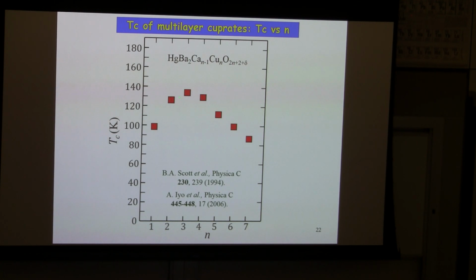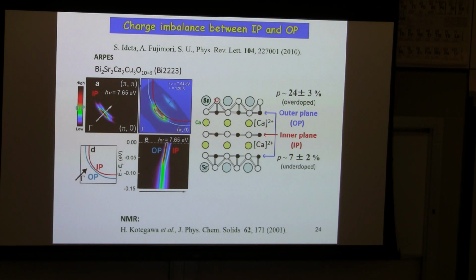But unfortunately, for exceeding 3 layers, there is some leveling off of the increase of TC. And when we go to 4, then TC unfortunately decreases. Okay? The reason why is the charge imbalance, namely that the hole density of the copper oxygen layers is different between the outer copper oxygen plane and the inner copper oxygen plane. You can see this is the estimate from the photoemission measurement as well as the NMR estimate. You can see that in the outer copper oxygen layers, there is a tendency to be overdoped, with hole density of almost 24%. But on the other hand, in the inner layer, the hole density tends to decrease remarkably.